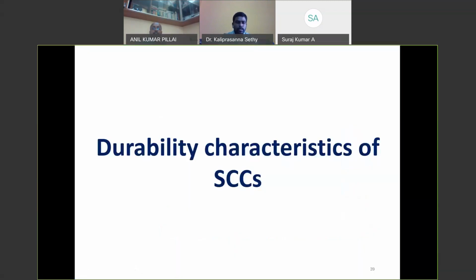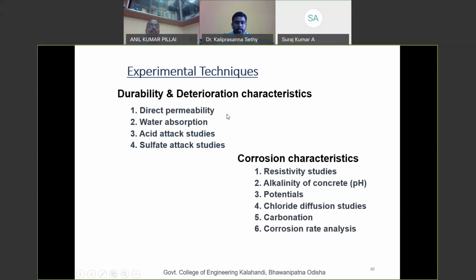And once we finished this mechanical property characterization and justified the mechanical characteristics, we have to go for the performance characteristics, that is the durability characteristics of this concrete. For that, we have conducted a number of tests: for durability, the water permeability test, water absorption test, acid attack test, and sulfate attack test. And for corrosion characteristics, we performed resistivity studies, alkalinity of concrete, that is pH value, and potentials, chloride diffusivity studies, carbonation, and finally we also went for corrosion rate analysis.